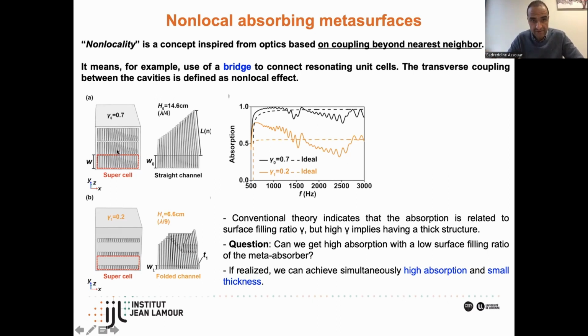Here the surface filling ratio is quite high, it's 0.7. If we would like to reduce the thickness, what we did, we took those channels and we bent them in order to reduce the thickness, okay? But if you reduce the thickness and you take the same unit cell as a supercell here, you have low filling fraction, and of course you have smaller thickness, but the quality of absorption is the orange curve. You can see that we lose a lot of absorption.